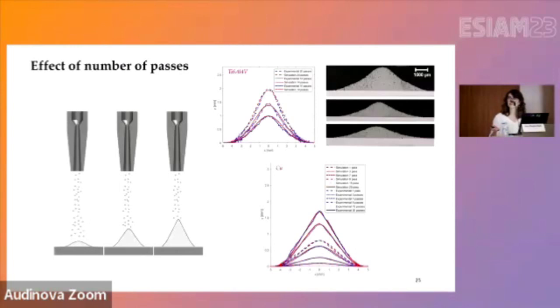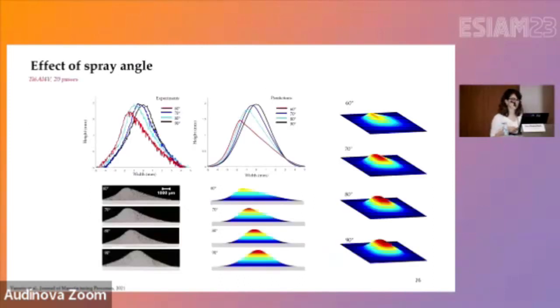Capturing, as you can see, the effect of the variation of the shape, in terms of the height and the width of the profile, as the number of passes increases. So we started from here, you can see for Ti-64 starting from 10 passes up to 20, and you can see even more clearly the variation from the Gaussian shape to the triangular shape for the case of the copper. So the model can, with very high fidelity, capture the shape as the number of passes is increasing.